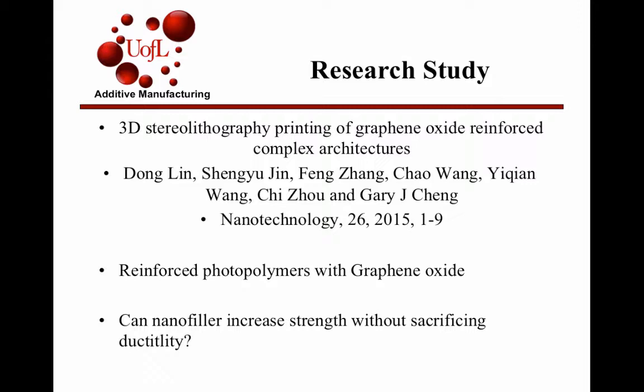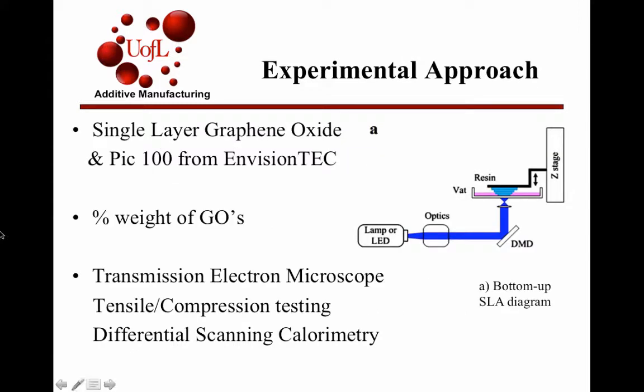As far as the manufacturing approach, you guys know stereolithography. This one was a bottom-up process for the printing process. The polymer they used specifically, they didn't really reference as the structure of the polymer. The only thing I could find was the PIC 100 from EnvisionTEC. That's the one that they used. And then the single layer of graphene oxide was embedded throughout the structure.